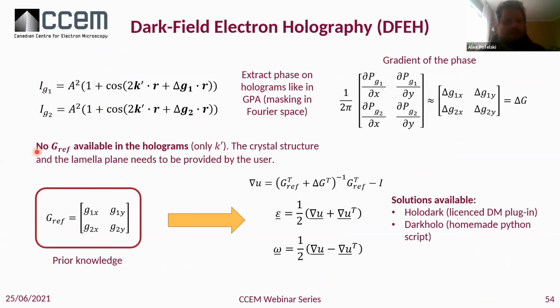The one point that is different is that we have no G_ref available, because this K prime, this carrier frequency, is not dependent on G at all. It's depending on the potential that you use on the biprism. So the crystal structure and the lamella planes need to be provided by the user. And here the calibration of your microscope matters. So this is a prior knowledge. And by adding that, then we come to the same equation again.